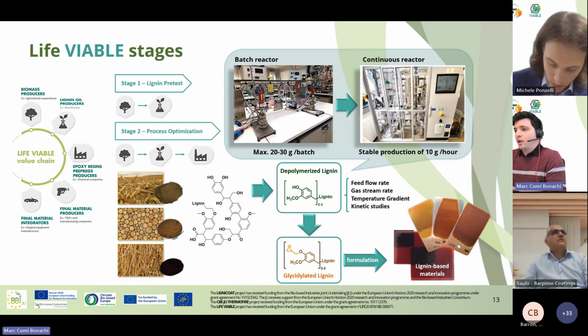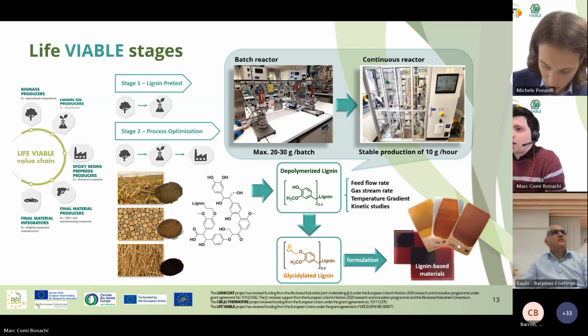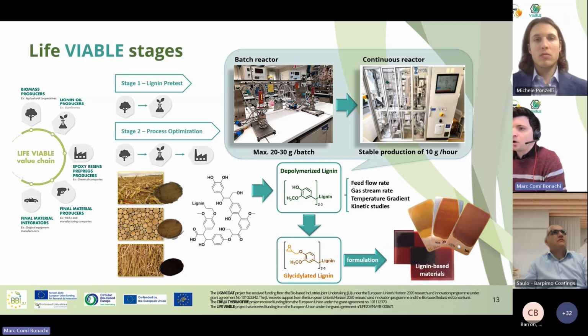So what we did later, when we got our depolymerized lignin with the parameters that I showed you before, is glycidylate this lignin. Here in the process optimization, we considered different things. The depolymerized lignin that we obtain is soluble. It reacts well with epichlorohydrin. What is the yield of the epoxidation? How is the workup? And different other parameters.